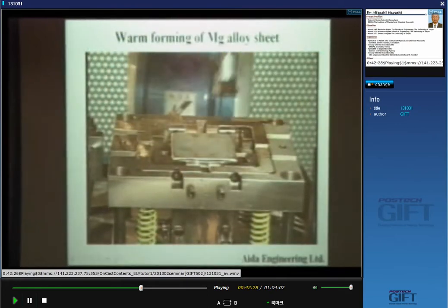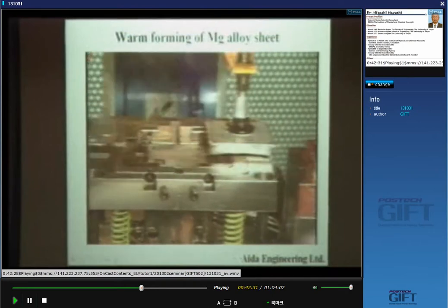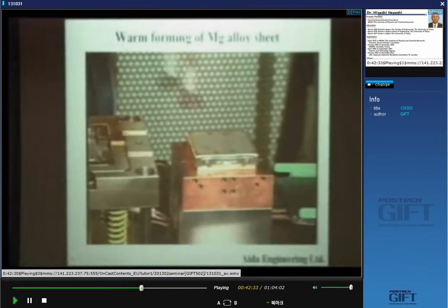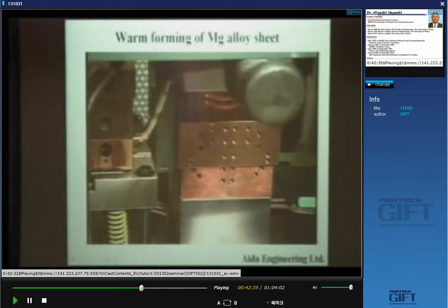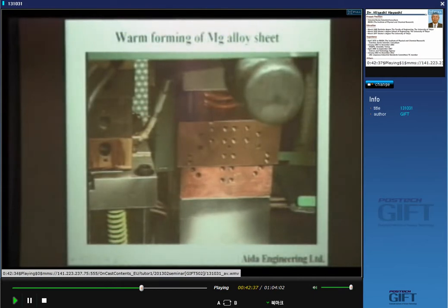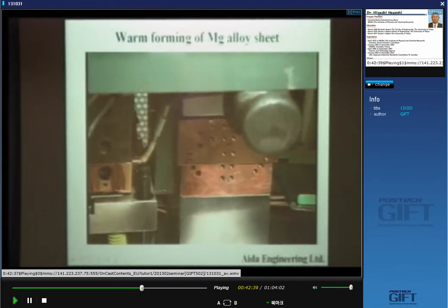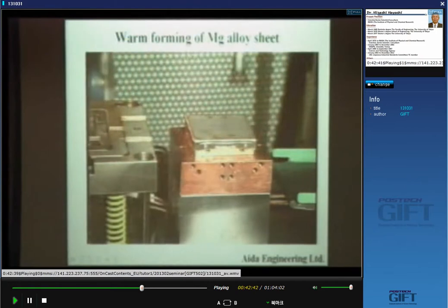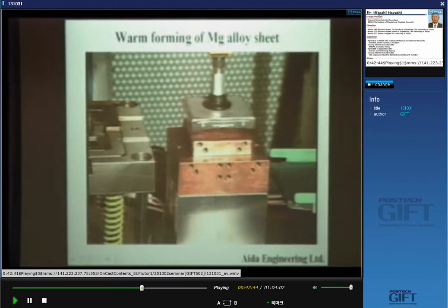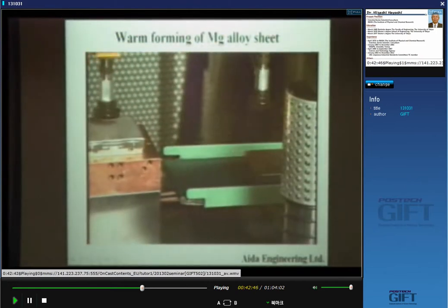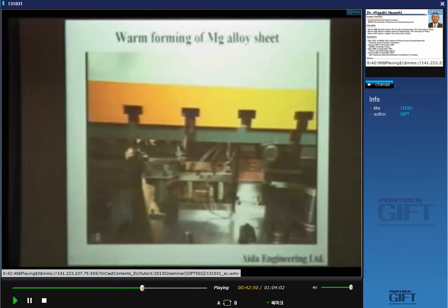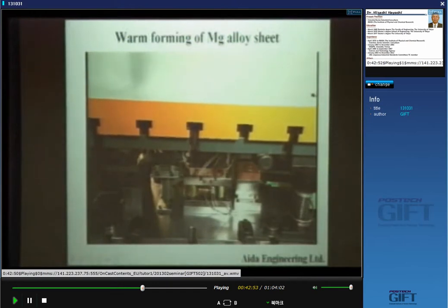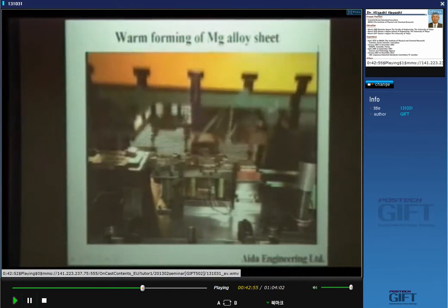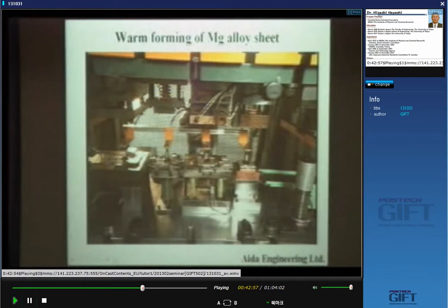And in the next process, the restriking and also trimming of the stamped box, and finally we can obtain the products. This method of warm forming of magnesium alloy sheets was developed more than 6 or 7 years ago, but unfortunately this technique is not applied in the actual stamping line.